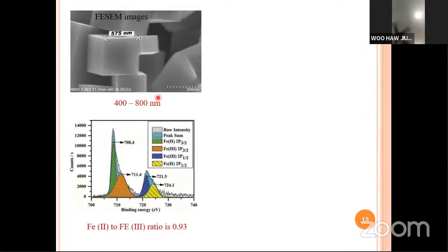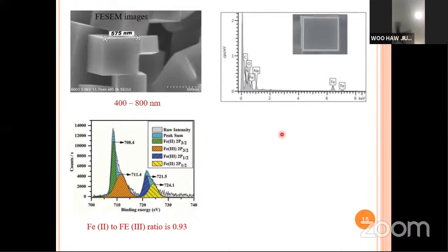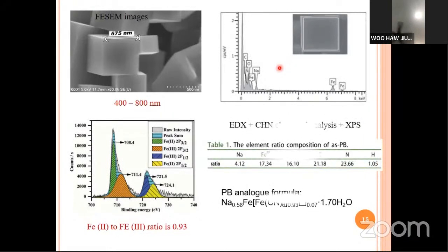And we also ran the XPS to look at the valence of the iron. So we have iron 2+ and iron 3+, and from the area under the curve, we found the ratio to be 0.93. We also did the EDX to look at the elemental analysis, and this is what we obtained. From this EDX, we obtained the element weight ratio. And we also ran the CHN elemental analysis to look at the amount of C, H, and N. Combining with the XPS result, this is what we obtained.